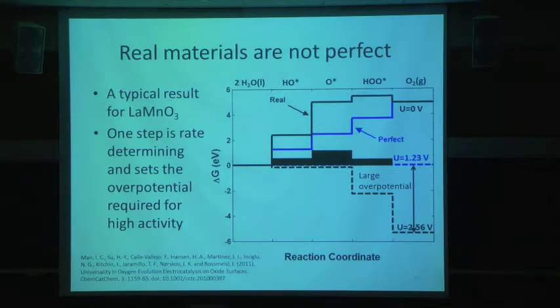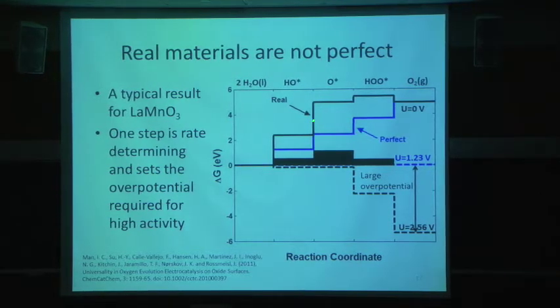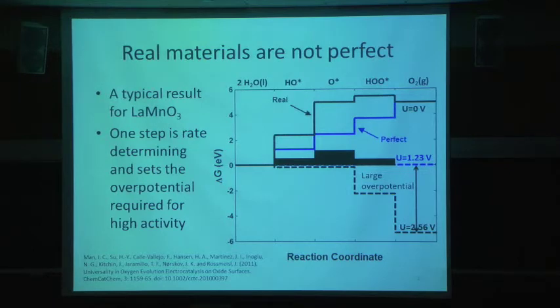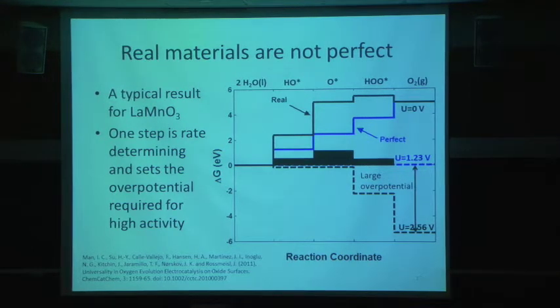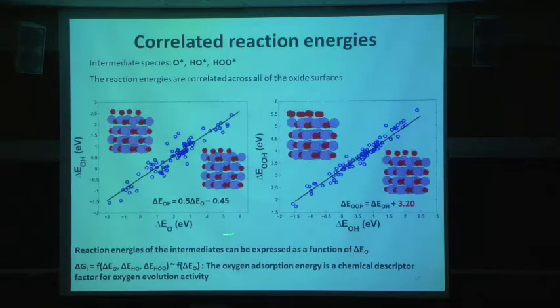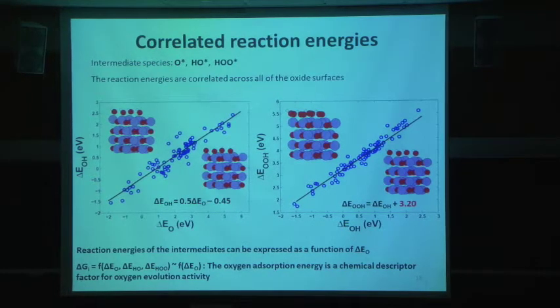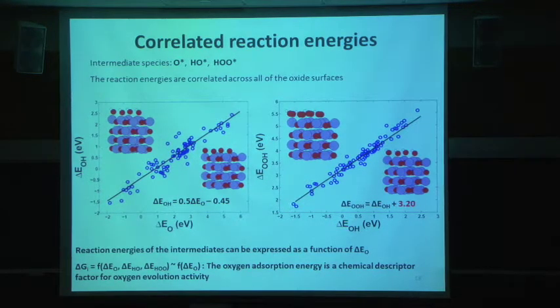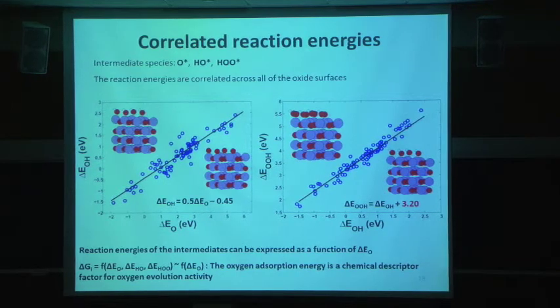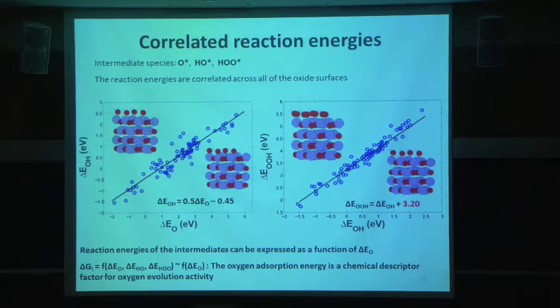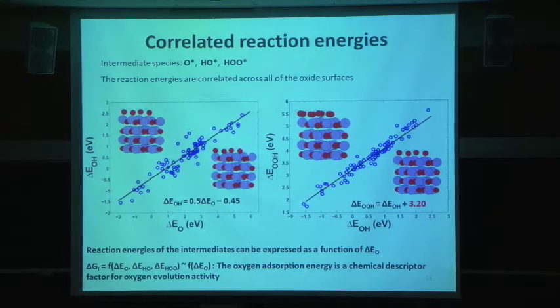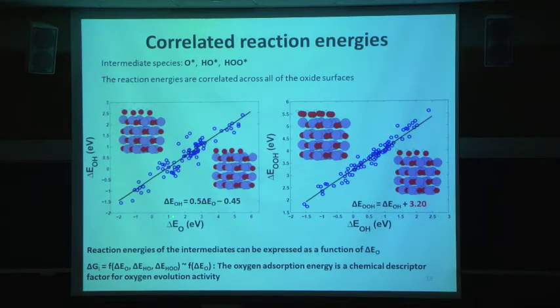Maybe we can find one that fixes this step and find one that fixes this step. But it turns out that those steps are not independent of each other. So if we plot step 1 versus step 2, you find out there's a reasonably good correlation in the energies between them. And now if I take step 2 versus step 3, you find an even better correlation. That means there's only one independent step in the whole mechanism that controls the overall reactivity. As soon as you fix one of these steps by picking a material, that determines this step. This step comes over here and determines that step.